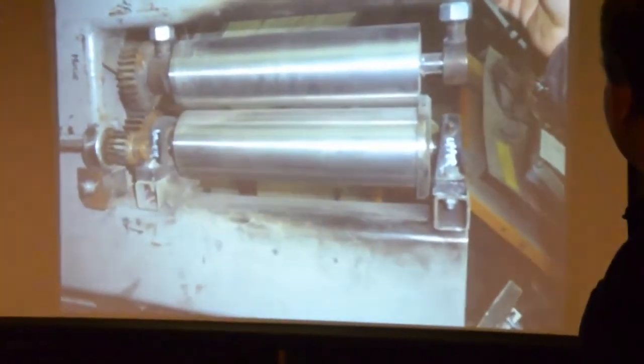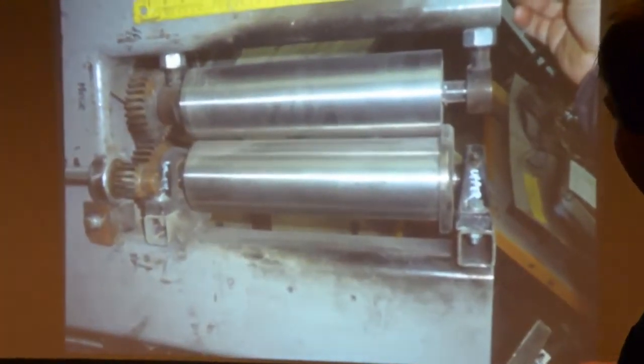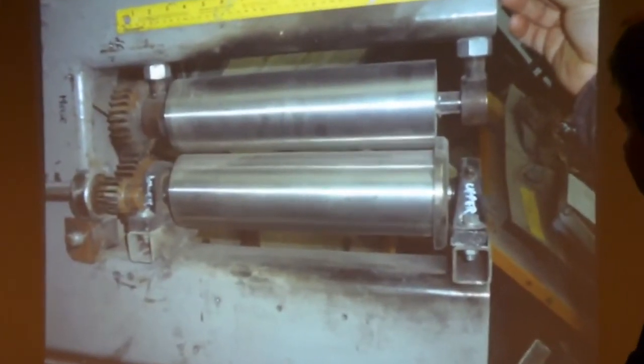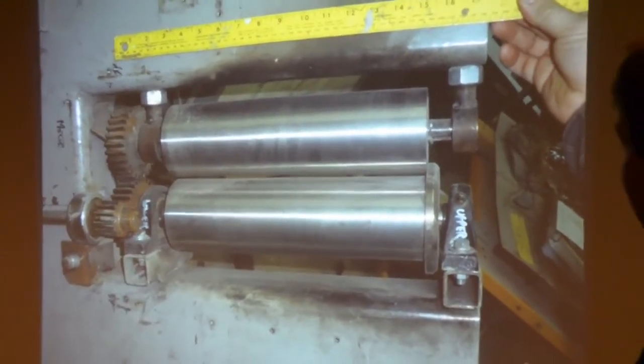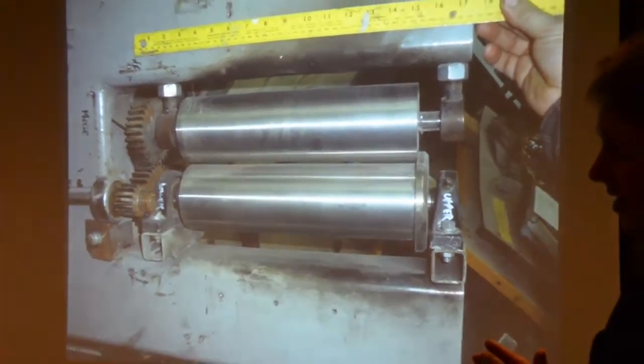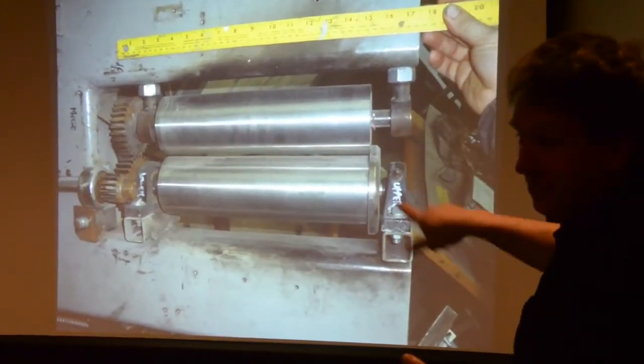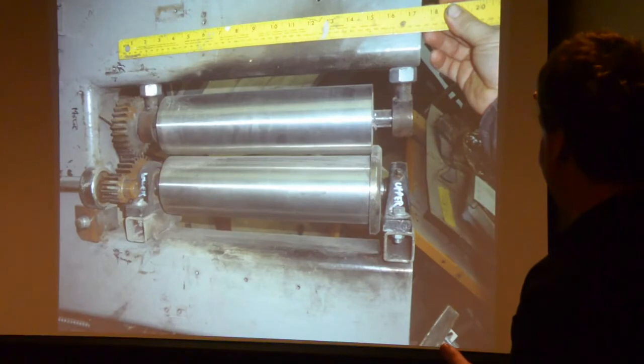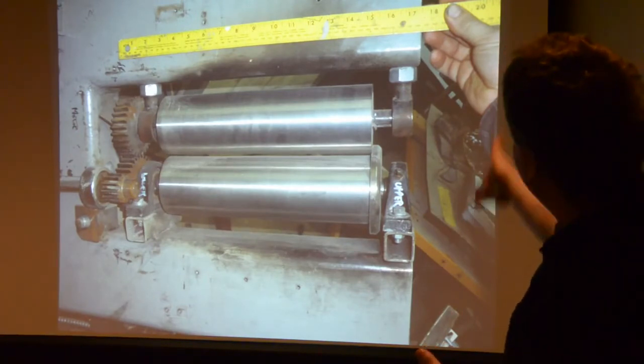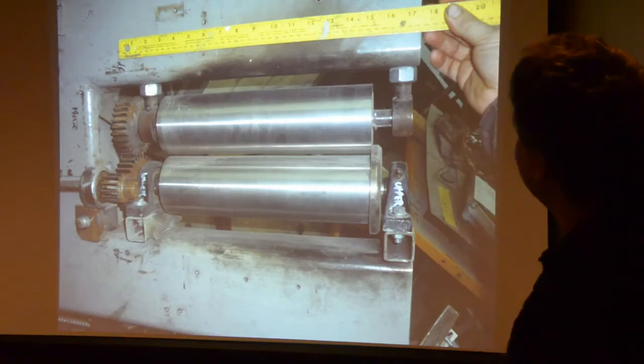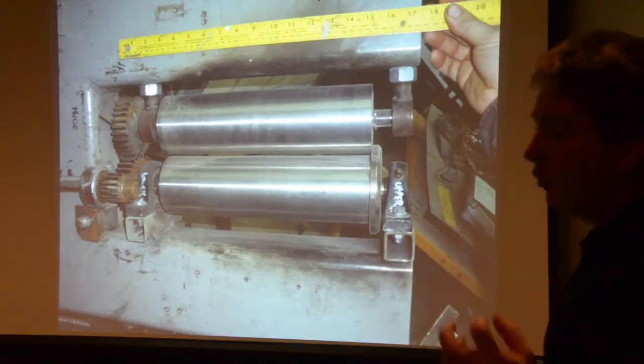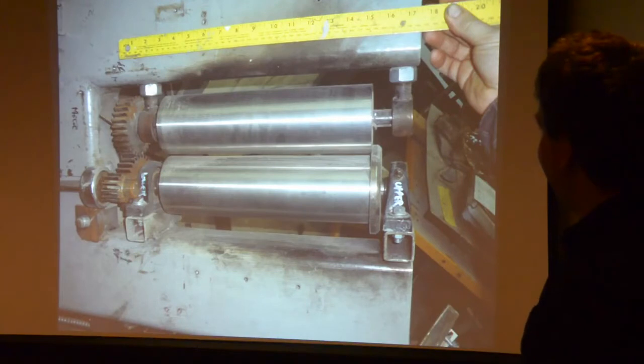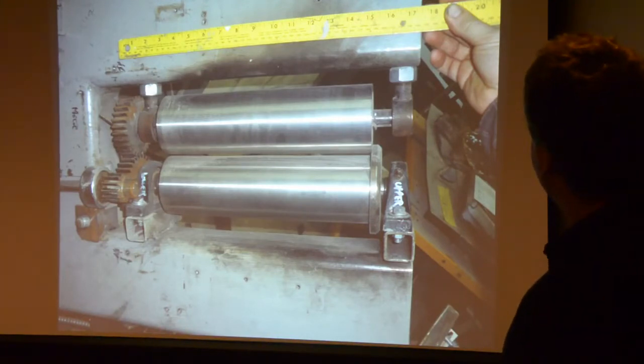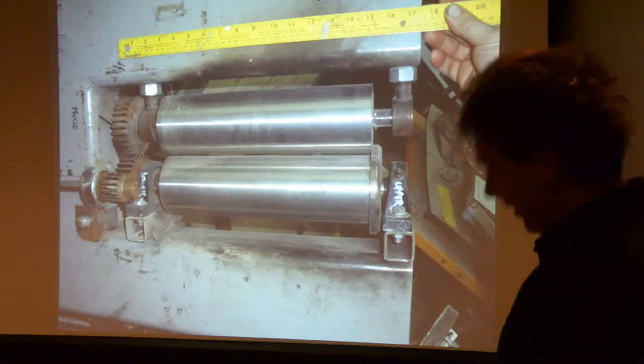But this is some stainless steel rollers for making my own stained glass. I got to put a lot of pressure on that. Doesn't have to be very hot. These rollers, you want them about room temperature. You can go off a little bit, but you do not want them hot because hot metal will stick to the hot glass, and then it'll wrap around the rollers. Oh man, have I done that a couple of times. That's why I've got this massive, 8-inch cross-section steel tube going, because anything less, it'll just pull that steel apart. It'll bend the axles. I've mangled gears and everything else, learning how to do stained glass sheet this way.